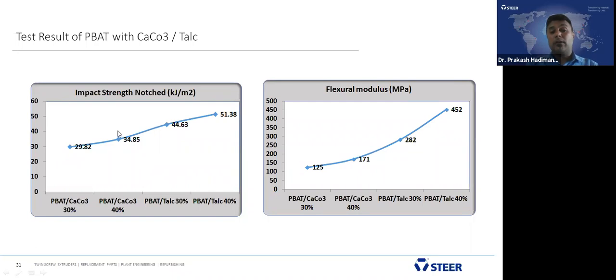But if you compare these two, talc is giving better mechanical property than calcium carbonate, because 30% of talc gives 44.63 kilojoules per meter square, and further addition to 40% gives 51.38 of the impact strength. That indicates that talc is giving better mechanical property compared to calcium carbonate. But when we come to flexural modulus, the stiffness, it is the same trend here also.